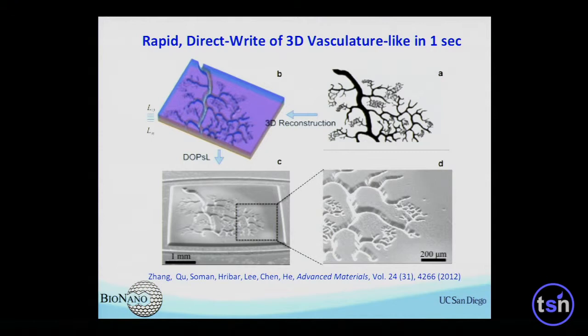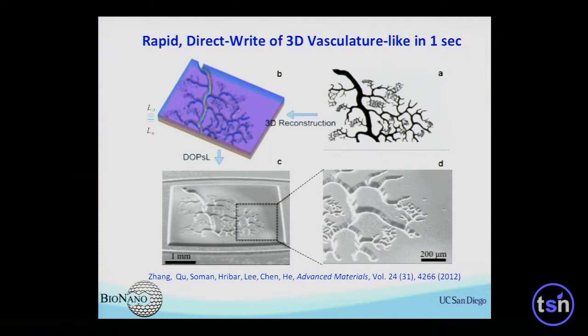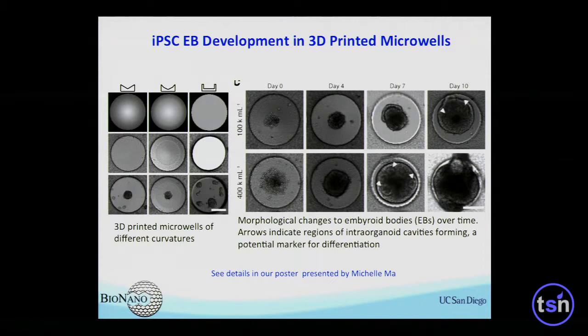With this kind of complex structure, those little channels are on the order of 10 microns, and we can print the whole thing in one second. It's really not point-by-point — we continuously build up these structures from the bottom all the way up. You can seed cells in the structure or encapsulate cells inside, and you can seed a second cell type on top or on bottom, allowing multiple cell types in co-culture.